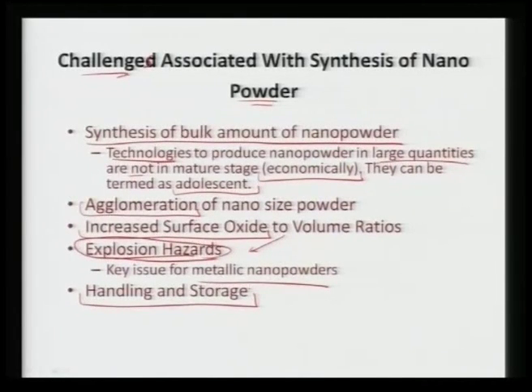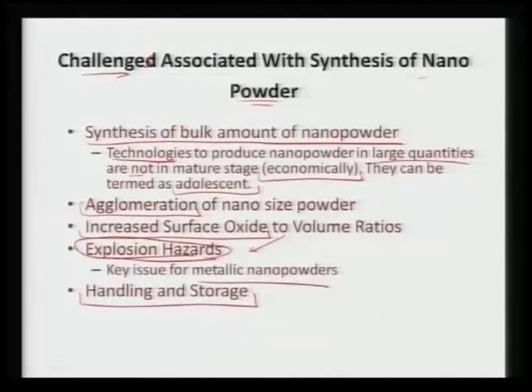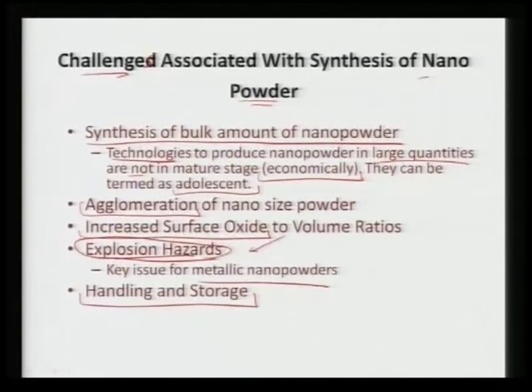Because of the high surface area associated with nano particles, if you want to make a component out of metallic nano particles, they tend to oxidize and can be highly explosive if they come in contact with the atmosphere. For handling all these, we need an inert atmosphere where we can handle them as well as synthesize them. Then comes the problem of handling and storage — we need some space for storing them in an inert atmosphere, which requires much space and becomes costly. Even while handling, if you are exposing them to atmosphere, it is creating surface oxide.